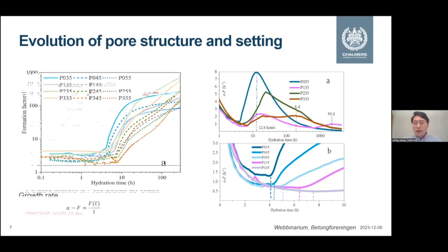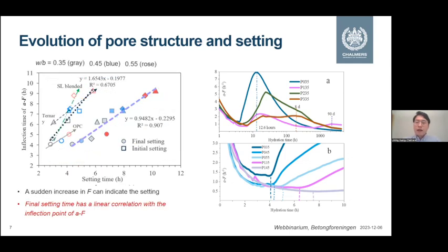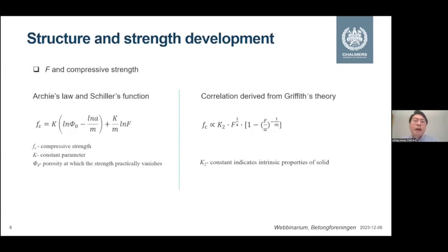And then furthermore, we connected the inflection point of this AF to compare with the final setting time and the initial setting time measured by the standard methods. We see that the final setting time has a good linear relationship with the inflection point time of AF, which means that these measured electrical properties can reflect the setting process of concrete with different SCMs, which is also critical for implementation of SCMs.